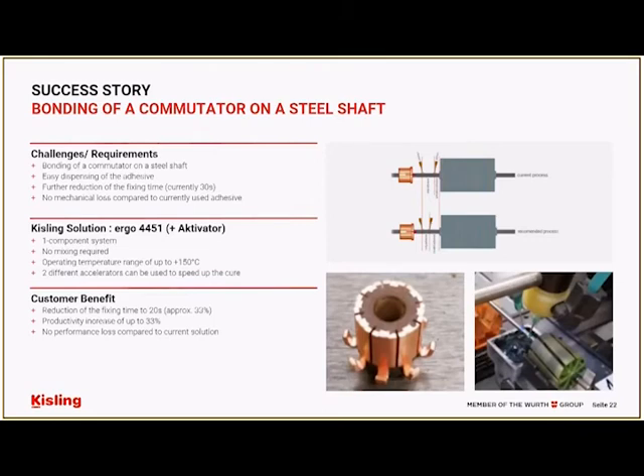Here is a one-part solution plus activator for bonding a commutator onto a steel shaft. In the bottom right-hand image, you can see two dots of material being dispensed. One is anaerobic and one is an activator. When the commutator is slipped into position over the two materials, they mix together, giving an instant bond. This method takes around 20 seconds. It's 33% quicker than the standard method and increased productivity by 33% with no performance compromise.